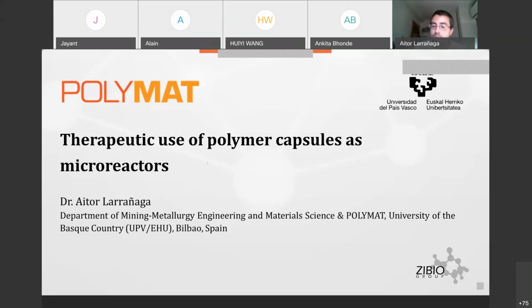And in case you want to improve the stability of these polymeric capsules, you can always go for a cross-linking reaction between the polymeric layers. For example, between the amines and carboxylic groups in the polypeptides, you can easily perform a cross-linking reaction to provide more stability to your capsules.